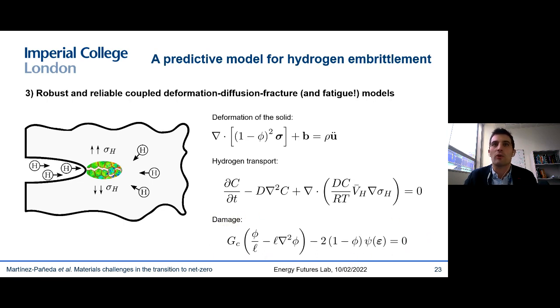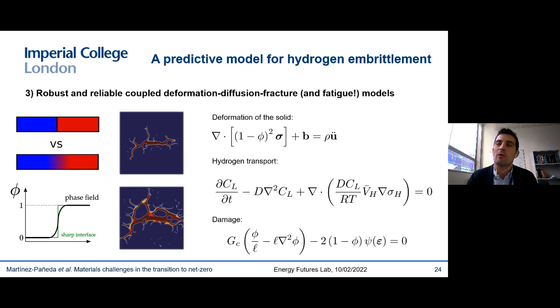So fracture occurs whenever the energy released by your solid is sufficient to separate two surfaces. So you have a toughness, the critical energy release rate of your material, and then you have the strain energy density, the energy that is accumulating in your solid and that will allow for a crack to propagate. And this is the foundation of fracture mechanics and Griffith's fracture mechanics. But the key thing is that from a computational perspective, it's not so easy to track how cracks propagate, because tracking discontinuities is, in general, a complicated mathematical and computational problem.